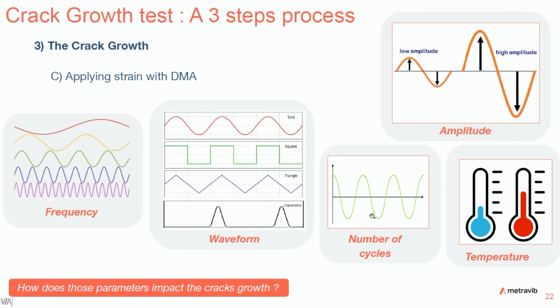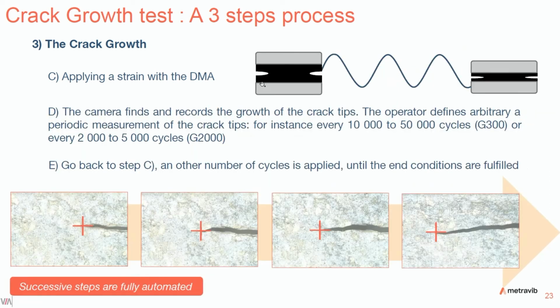So how can those parameters impact the crack growth? We apply a strain with the DMA, and the DMA finds and records the growth of the crack tips. To give you an example, the operators define an arbitrary periodic measurement of crack tip growth, for instance every 10,000 or every 50,000 cycles, depending on the tearing energy they want. For instance, 50,000 cycles for a low energy, and 2,000 cycles if the tearing energy is much higher. After that, we go back to step C, that is to say, applying another strain, and so on, until the end conditions are fully fulfilled.